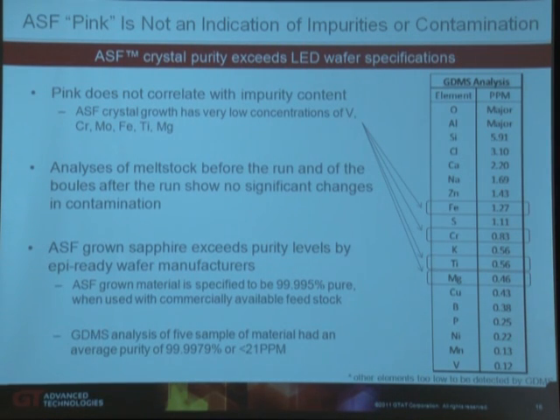One common concern was that color is caused by contamination. So one of the critical analyses we performed was to measure the raw material, or the aluminum oxide, for contamination levels, and then measure the actual sapphire crystal after the crystallization process and measure the contamination levels. What we found was that during the ASF growth process, there is no additional contamination of the sapphire, meaning the contamination levels before and the contamination levels after are exactly the same. So we don't put any contamination into the sapphire crystals.